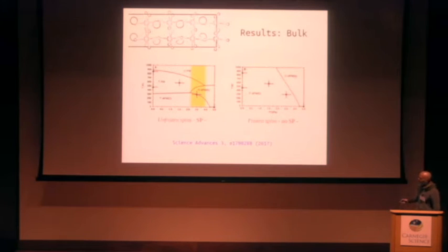Also, at zero temperature but under pressure, we get good agreement with experiments. And then we found a very exotic region in our phase diagram that involves a double reentrant phase. This is this region here, which I put in yellow. If we start from some point around 2.5, for instance, and start heating up the system, we start from some tetragonal polar phase with antiferromagnetic order, we then stabilize an orthorhombic non-polar phase, which is still antiferromagnetic, but after heating it up further, we get, again, a tetragonal polar phase, but in this case paramagnetic, right?